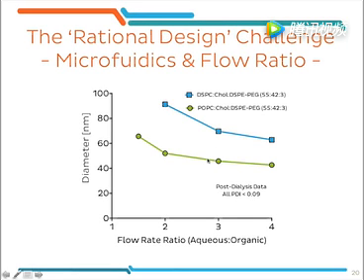And the liposome formulation marked in green here, the lower liposome formulation, contains a more flexible lipid, the POPC lipid, that has a tendency to form smaller particles. So if I was making these liposome formulations in a beaker, I would actually get liposomes of one size with a relatively high polydispersity. But by controlling the liposome self-assembly through defined microfluidic mixing parameters, I can make liposomes of different sizes with low polydispersity.